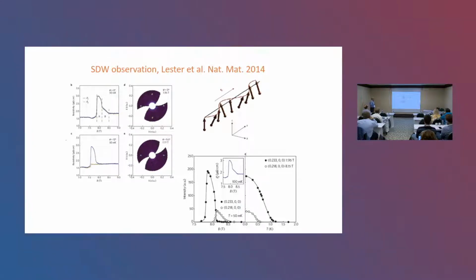Moreover, this notion of nematicity was more or less destroyed when in 2014 there was an SDW observation in that phase. And you see that if the theta angle is such that the magnetic field is along the C-axis, we have 4 spots, so 2 equivalent directions, no difference in the resistivity along A and B. If you tilt a little bit, then 2 of the spots go away, and there is a big difference in resistivity. So the conclusion is that you have an SDW, and then with the magnetic field you can align the domains, and this is the anisotropy that you could see, and not directly related to nematicity, which cannot show any SDW.